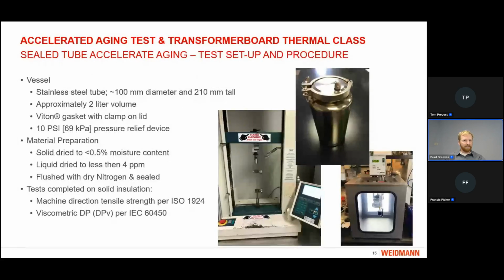So looking at some details of how this testing is done, we use a vessel, a stainless steel tube, approximately 100 millimeters in diameter, 210 millimeters tall. It's approximately 2 liter volume, slightly larger. It has a clamp-on lid shown here with a Viton gasket to ensure that we have a good seal on that lid. And it is fitted with a 10 psi pressure relief device. That pressure relief device is used first to keep a consistent pressure within that aging vessel, but also to ensure that we're not building up significant pressure where we have a potential safety concern within the test lab.